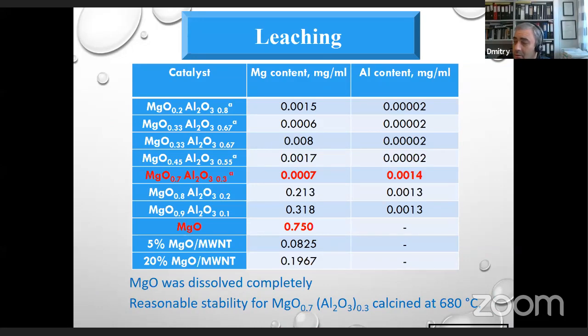I should now return to leaching. As I mentioned before, when we used magnesia, it dissolved completely. So the magnesium content in the liquid was extremely high. Compared to magnesia, this catalyst had a very low concentration of magnesium in the liquid phase, almost at the level of detection limit. So this material demonstrated reasonable stability when it was calcined at 680 degrees C.